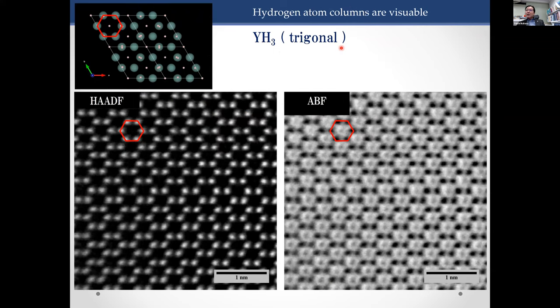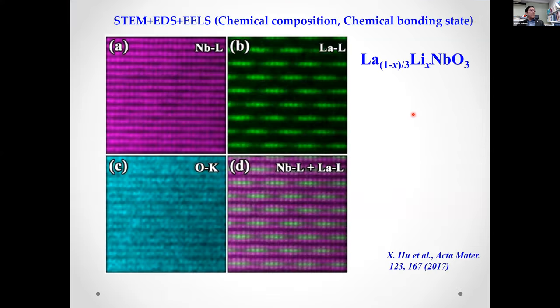You can even see the hydrogen column. This is yttrium hydride, which has a trigonal structure. This is the structure of yttrium hydride. In the HAADF image, you only see the hexagonal structure of the yttrium columns. You can't see the hydrogen, but in the ABF image, you can clearly see the hydrogen column, which is at the center of this yttrium hexagonal structure. So this is a very powerful technique.